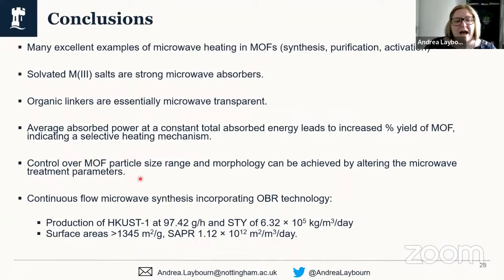I've then showed you that we can control the MOF particle size range and morphology by altering the microwave treatment parameters. So this can potentially also be used in combination with chemical parameters as well, such as modulators, to give you extremely high control over the particle sizes and the morphologies that you're producing.